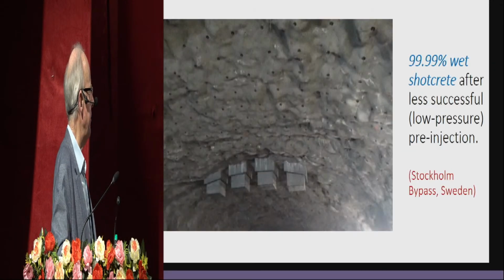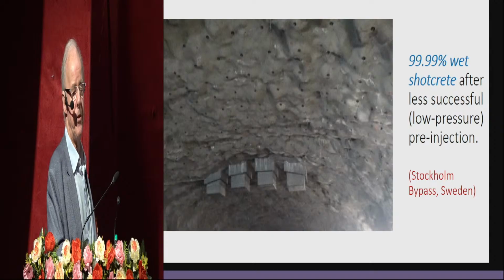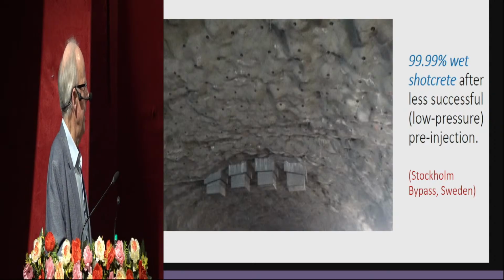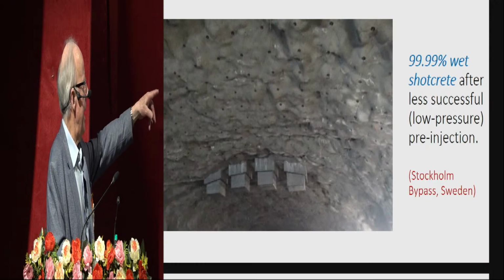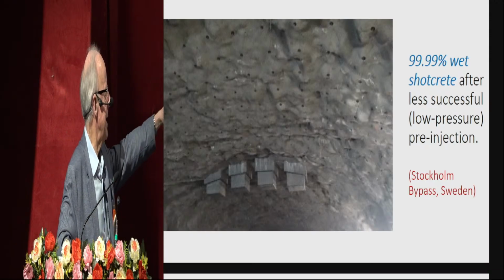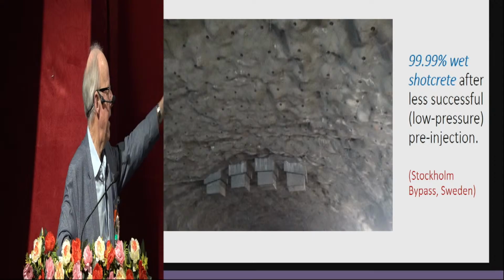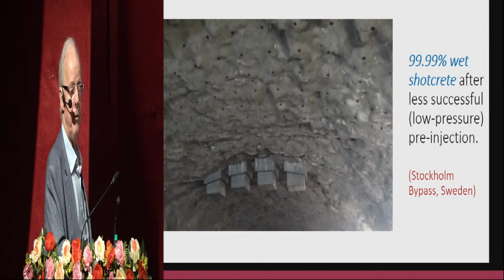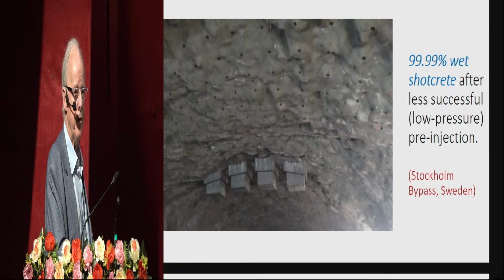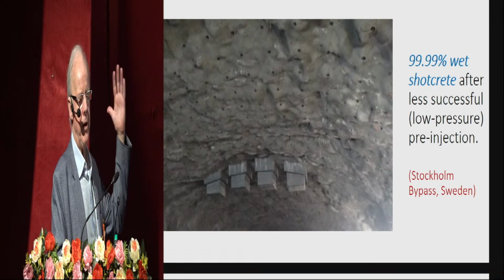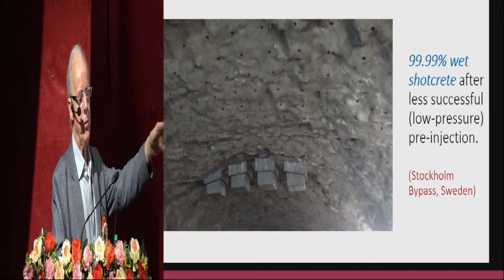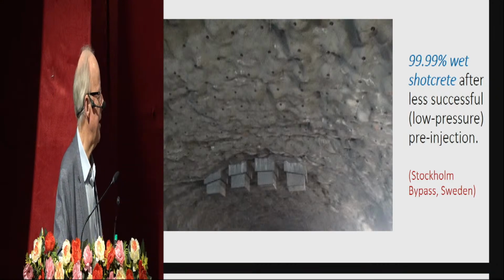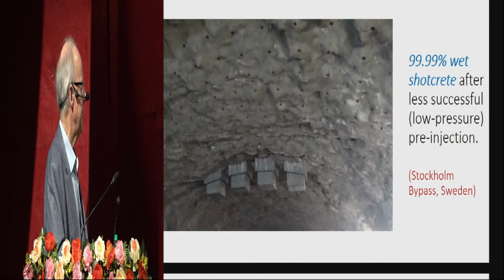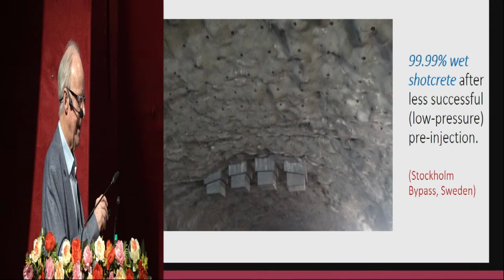And the next picture is 99.99% wet shotcrete, a dark, kind of a strange dark color. And there are just a few areas on the right, a little bit lighter shotcrete. You can see nearly at the edge of the photograph. That's dry shotcrete. So the Swedes, they're not using high enough injection pressure. They're only injecting 1 joint set. There's water coming in, and the 2 or 3 joint sets that are not properly injected. So a huge amount of environmental damage.